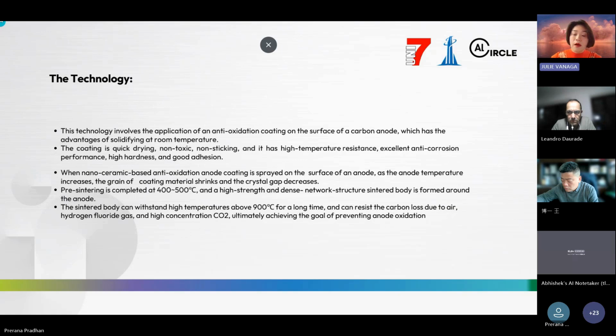And also it's washable. Some customers ask us if they can wash off the coating. Yes, you can use water to wash it off. It won't stick to the electrolyte and other components, ensuring smooth pot operation. Most importantly, it boasts excellent high temperature resistance, anti-corrosion performance, high hardness, and strong adhesion. These are all the critical properties a coating needs to survive the harsh, high temperature environment of the electrolytic pot, above 900 degrees, and corrosion from hydrogen fluoride gas, high concentration CO2 and air.